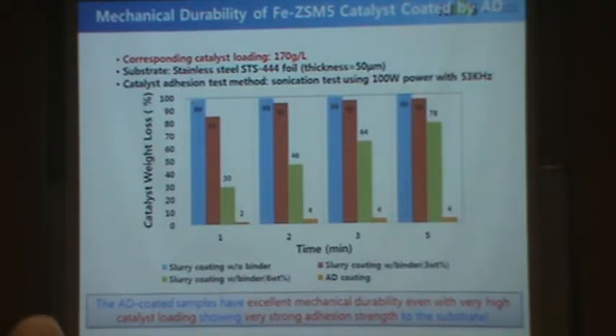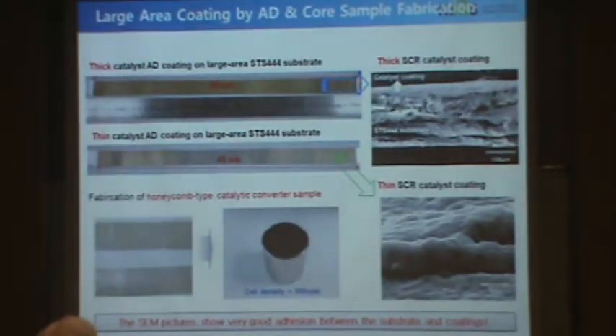So our coated samples have excellent mechanical durability, even with very high catalyst loading, showing very strong adhesion strength to the substrate. And then we tested the NOx performance using the sample. So people can think, oh, this might be dense, so there might be no catalytic activity, because it's dense to get strong adhesion. So we tested the NOx.